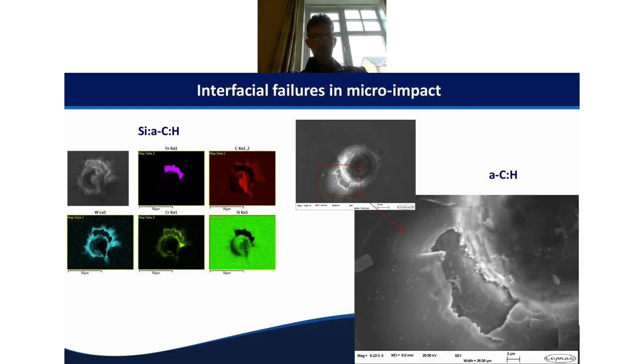So if you look in a little bit more detail, you can really see that interfacial failures are the cause of the headache in these coating systems. So you see you're getting exposure of these sublayers, and in this case, exposure even of the steel substrate underneath.